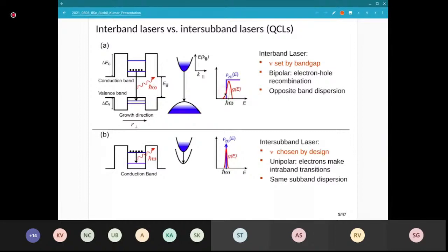So the frequency is set by the band gap. In QCLs, we do not use holes. So these are n-doped devices, no p-doping needed, no holes are needed. By making this quantum well, for example, this is gallium arsenide, aluminum gallium arsenide, and adjusting the thickness of the well, you can change the separation between these levels. If you can somehow have electrons occupy a higher energy subband, so achieve a population inversion, that's how you get optical gain. And then when you put that in a cavity, you can get a laser. So that's the concept. It's easier said than done, obviously.